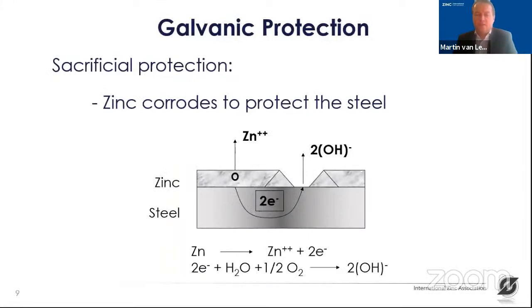How does that work? In case you have an undamaged coating, the coating, as we have seen, can act as a barrier protection, as a barrier coating. But if the coating is compromised, if there's a holiday in the coating or a scratch or any other kind of damage, and the bare steel surface becomes visible, then the zinc starts to work as an anode. The zinc can react with water in a galvanic cell if there's water on the surface. And instead of the steel starting to oxidize, the zinc will sacrifice itself and will form zinc corrosion products like zinc hydroxide. It can fill up the scratch to give an additional protection to the steel. And it will make sure that instead of the steel showing red rust, the zinc will protect and will corrode instead.